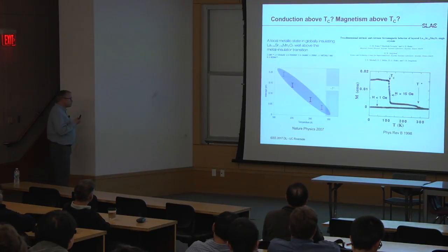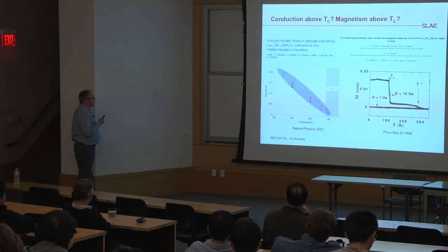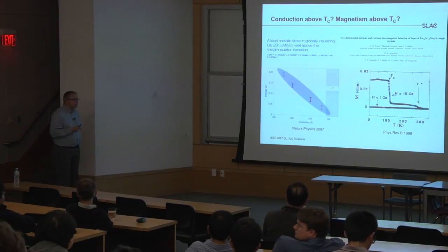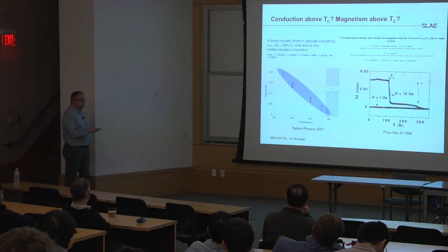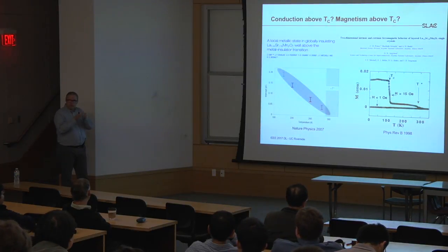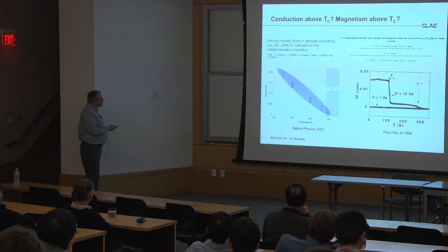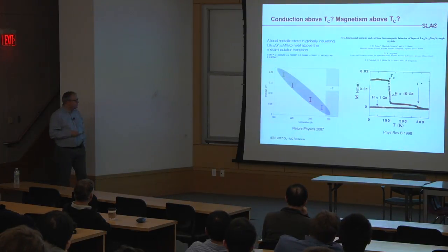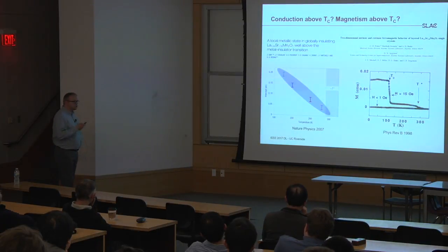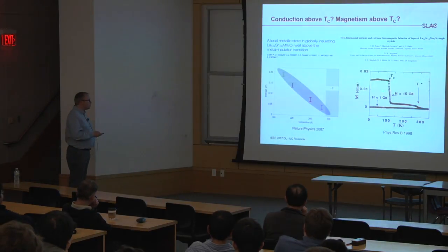From an electronic point of view, much later people also found that the full metal to insulator transition happens much later. While most of it is gone at 120 Kelvin, if you monitor the photoemission intensity from the Fermi edge, which essentially gives you how many electrons are at the Fermi energy, that tells you whether it's still a metal or an insulator. People found that this only fully disappears at around 300 Kelvin. So apparently, although this material is supposed to do both of these transitions at 120 Kelvin, they keep a certain portion of this property all the way to 300 Kelvin.